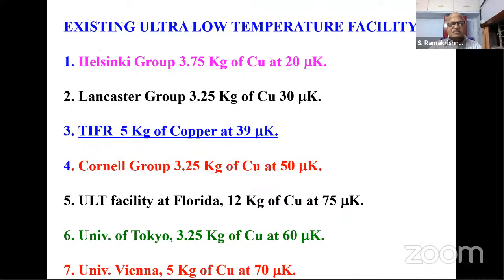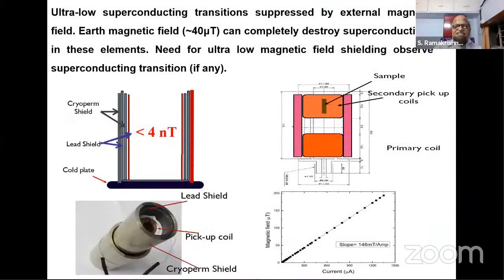Now we have a fantastic ultra-low temperature system, and can we try to see what is the case for bismuth? One of the major problems with superconducting discovery is that when you have such a low Tc superconductor, its critical field is also going to be small. The magnetic field will destroy this superconductor, which is well known.